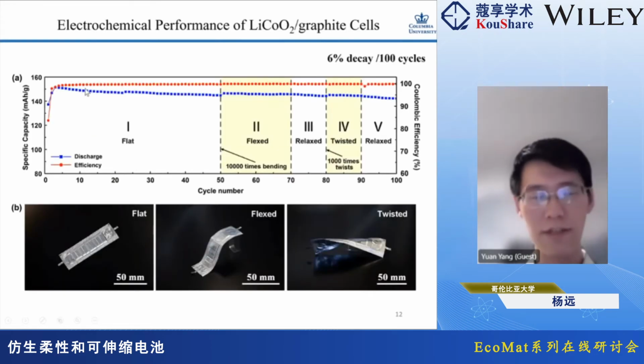We first tested the cells in the static condition, and you can see the cycling is pretty good. The capacity loss is about 6% after 100 cycles. During the cycling, we also bent it 10,000 times and twisted it 1,000 times. Then we tested the performance in the static condition, the flexed condition, and the twisted condition. You can see the power output, the cycle life, and the capacity are quite stable.